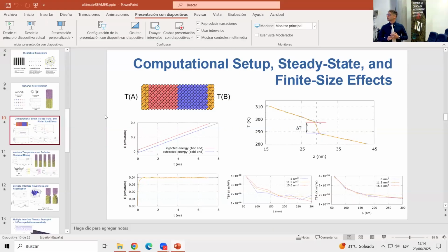I mean, it depends on what your purpose is, because here we had some specific purpose, chasing technological applications, and a very simple description which assumed an infinitely sharp interface and temperature drop would have worked. Of course, if you are interested in the interface properties of the material to a more refined extent, you should consider the interface as a physical system itself. You should really try to look at what is going on there, consider the interface thickness, consider the interface as a region where the thermal conductivity is way higher than the two materials, and this has to do with the particular interactions between the two of them. But it really depends on the specific interest you have.